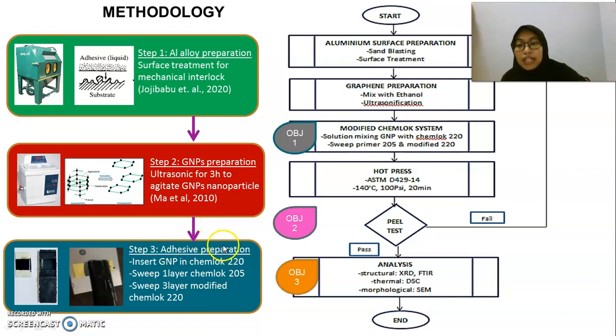Next is step 3, adhesive preparation. Insert the GNP in the Chemlock 220. Then swab the first layer of Chemlock 205 as primer. Then swab three layers of modified Chemlock 220. This modification will achieve objective 1. After the sample is prepared, we vulcanize the parts by hot press with ASTM D429. Then, after the sample is completed, we undergo the peel test for mechanical testing and to correlate between these materials to achieve objective 3.